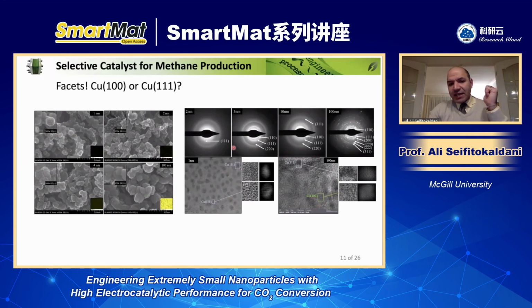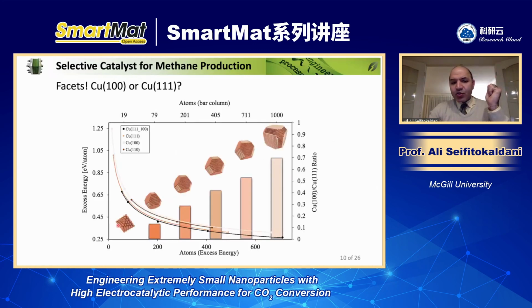And here you see again, for very small particles, unfortunately, we couldn't go lower in terms of the size. We would love to be able to do it, but our TEM here at McGill is not able to detect particles smaller than that for the crystallinity. But obviously, as you see, when the particle size increased, we observed more signals from other facets, kind of proving or supporting what we just mentioned in the previous slides, that you have more 111 here and then more 100 here.